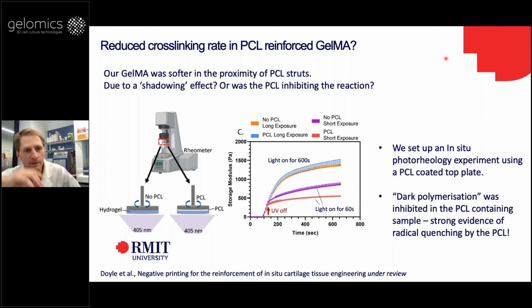So what we did was we set up this experiment, an in situ photorheology experiment, where we coated the rheometer plate in PCL, and the light is being shone in from underneath here. In this case, we're using LAP and 405 nanometer light. And what we did was we turn on the light, and when it's on continuously, with and without the PCL plate, we see that the stiffness evolves very similarly in each case. So basically, it makes no difference if the PCL is there when the light is on continuously. But the behavior is very different if you turn off the light after just 60 seconds.